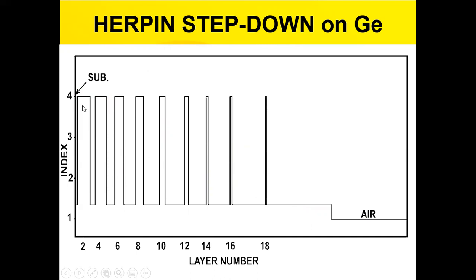The first piece is going to have an index just a little less than the index four of a germanium substrate. So it'll be mostly germanium and just a little bit of the low index. There'll be a layer like this over on this end. For the next layer it's going to be not quite as much high and a little bit more low here and here.